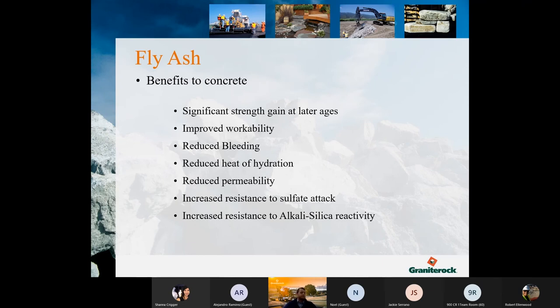So fly ash, just like slag, reacts with the byproduct from the cement reaction. Again, the reason it creates strength in later stages, it doesn't react with the water up front, it reacts with the cement reaction. So that has to take place, and then fly ash starts to go to work. Again, this helps with permeability because it is creating more crystals with the same amount of cementitious material.